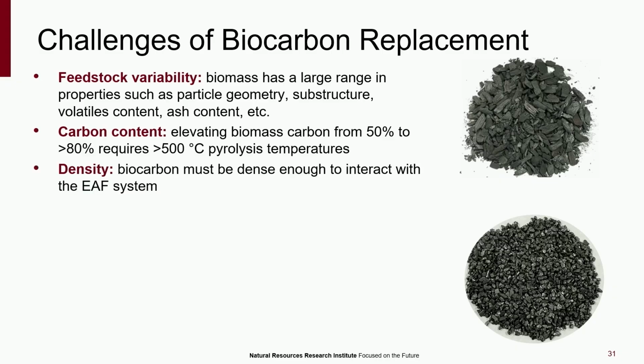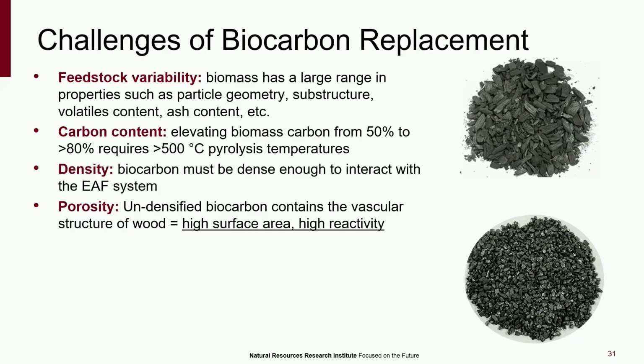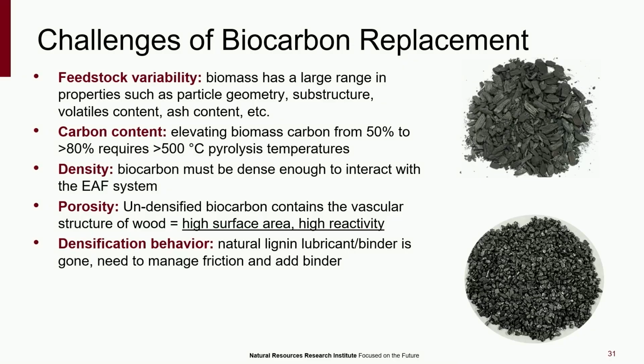We also know that it needed to be dense. Regular biochar does not interact well in the EAF environment. It just kind of floats on top, or if it's too light, it just flies off with the flue gas, so it's not going to interact if it's not dense. Also with porosity, if it's too porous, which in some cases you want a porous biochar, in this case it turns out to be too reactive, and so we had to figure out how to control the porosity, leading into densification. So we ended up densifying our formulations at those high pyrolysis temperatures.